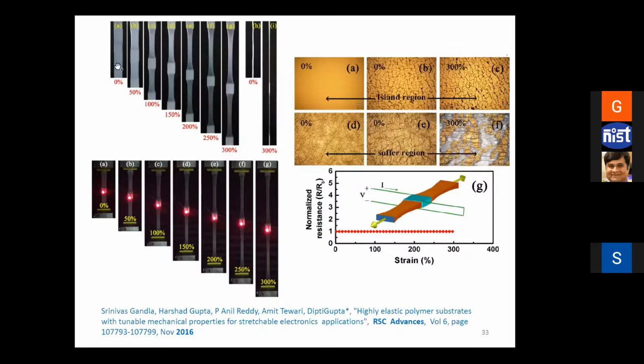So the first picture over here, if you see, is basically a soft material. In between, there is a rigid portion. There are some slight protrusions, if you can see over here. These are the rigid part of it. This can be stretched up to 300%. And now in this 300% figure, you can see this white portion clearly, which is the rigid portion. So by doing this kind of recipe, we are selectively able to create rigid portions in between these soft portions, which can stretch up to 300%.